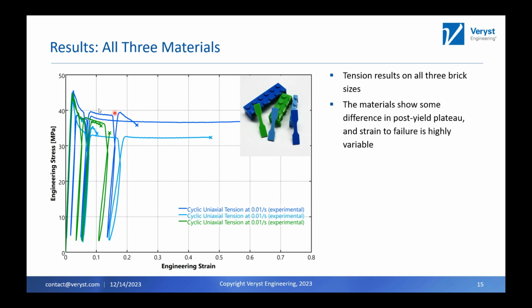Overall, there's not a lot of difference between these two, which we wouldn't really expect. The stress plateau seems to be lower here on this light blue one. It's hard to say if that is a material difference. I have no idea what these bricks have been through. I think they were bought at a thrift store, so these have been through how many kids and how many UV cycles, we don't know. One of these bricks could be 5 years old and one could be 15. In a real use case, we'd want to really know the history of these bricks, but again, you just see a little bit of noise in the force, but overall you're getting the same response.